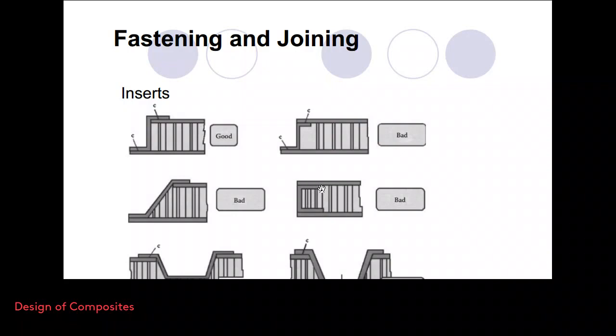Next one, this design is also not acceptable, because once you have a bending on either side, perhaps this sharp corner will begin to exert a force on the laminate. If this bond fails, because this is the first place that we expect to see a failure, once this bond fails, it will begin to apply a force to the upper laminate, and complete debonding from the core materials can be seen in either direction.